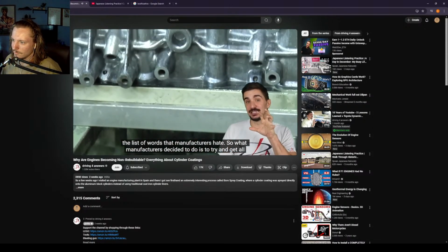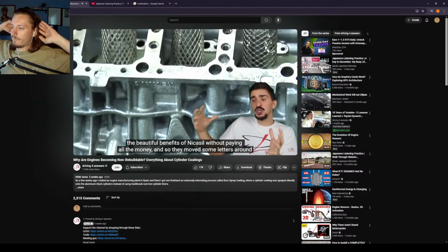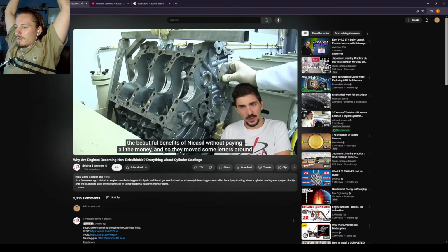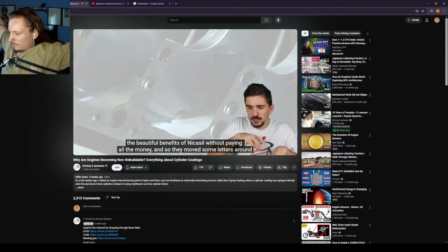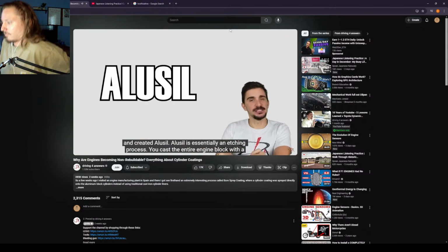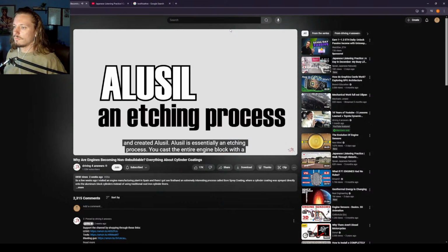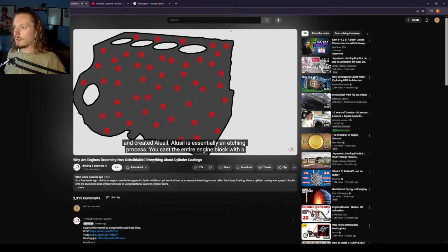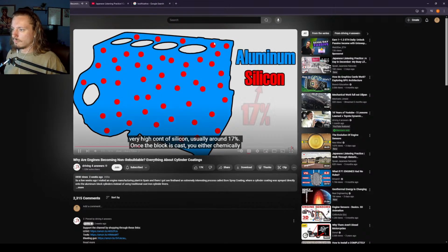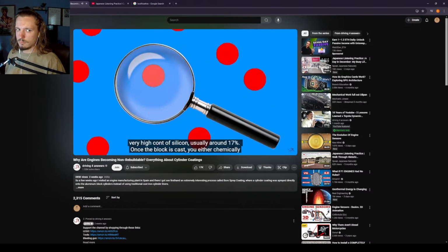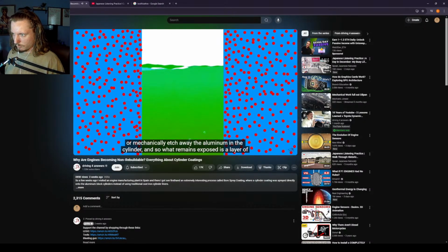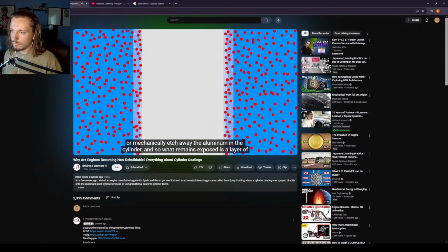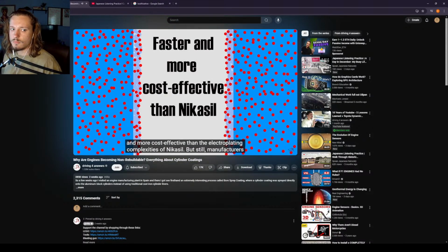So what manufacturers decided to do is try to get out all the beautiful benefits of Nikasil without paying a substantial amount of money. And so they moved some letters around and created Alusil. Alusil is essentially an etching process. You cast the entire engine block with a very high content of silicon, usually around 17%. Once the block is cast, you either chemically or mechanically etch away the aluminum in the cylinder, and so what remains exposed is a layer of silicon, and silicon is a durable and hard-wearing material. Overall, the process is much faster and more cost-effective than the electroplating complexities of Nikasil.